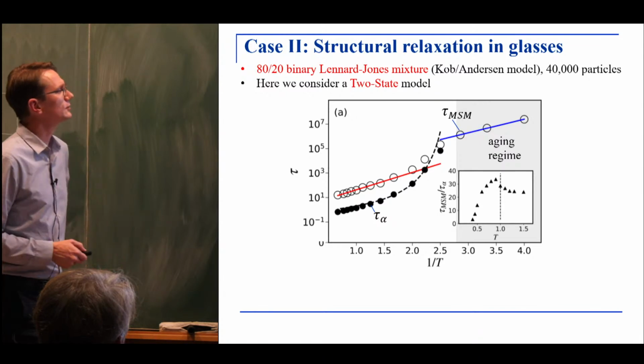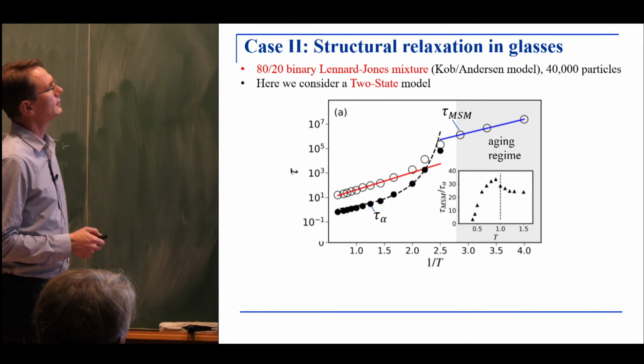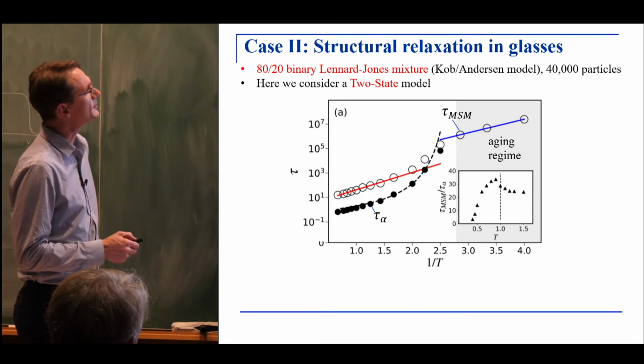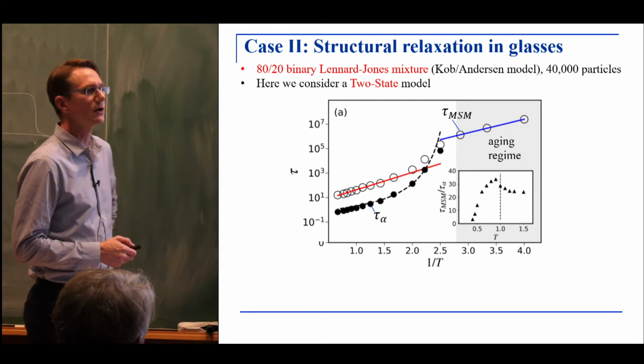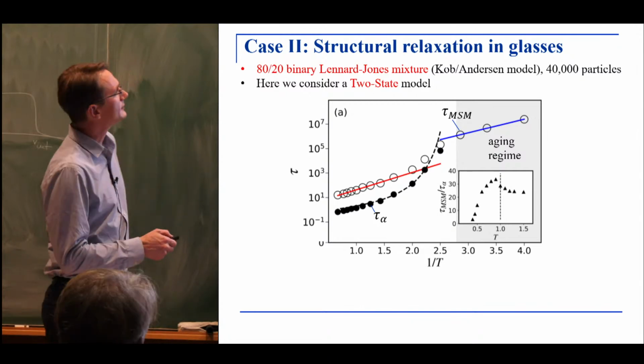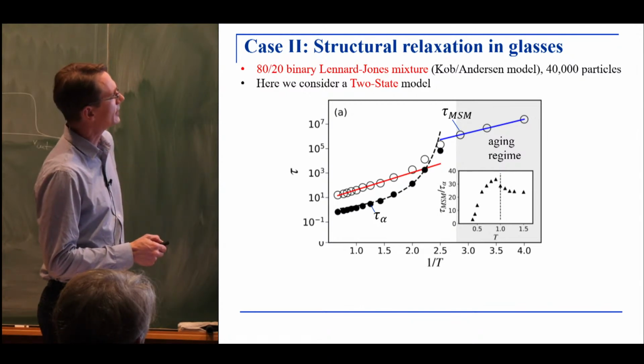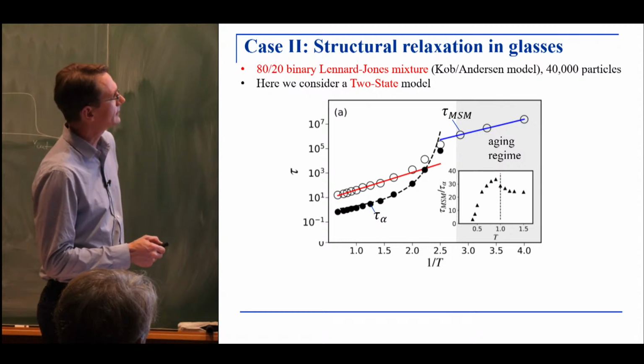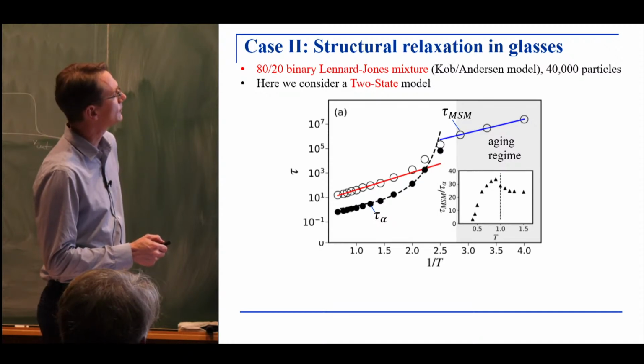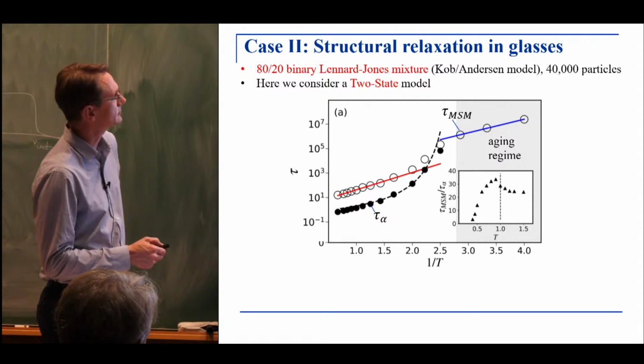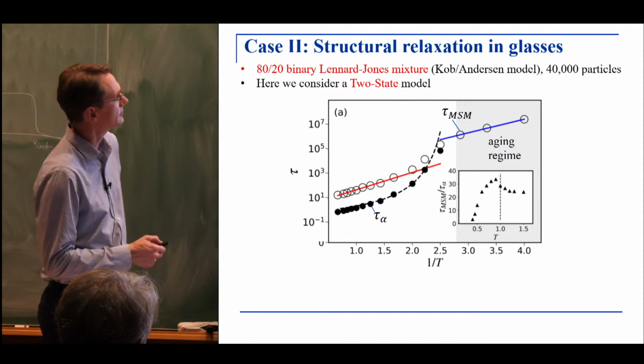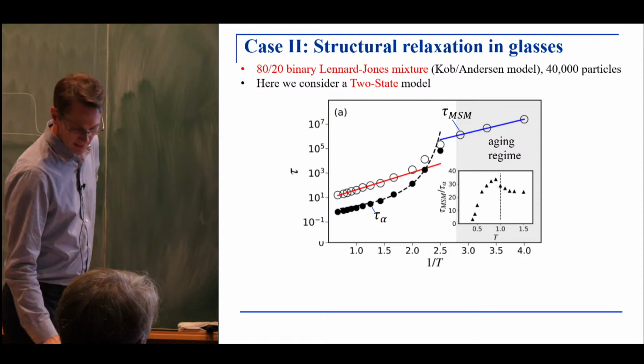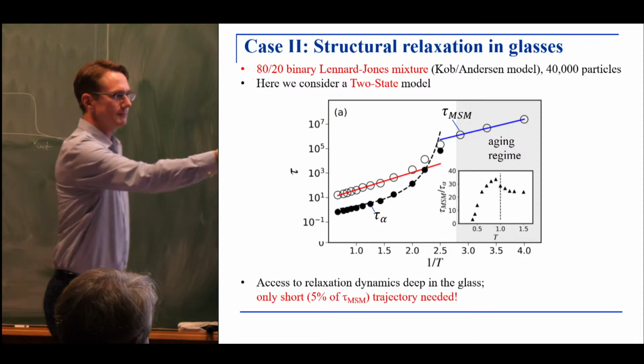Okay, so what do you see in this graph in this Arrhenius representation? First, please focus on the open symbols. The open symbols is the time scale that is found from this Markov state model. And you can see that there's a bit of an Arrhenius law at high temperatures, then there is a faster than Arrhenius rise, and then in the low temperature regime, where the system is in principle no longer equilibrated, we observe a different behavior with, again, an Arrhenius type of law, with a different prefactor, but a slope that's not too different. Now, one thing I want to emphasize is that